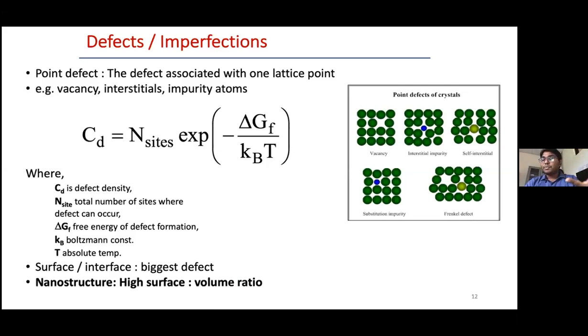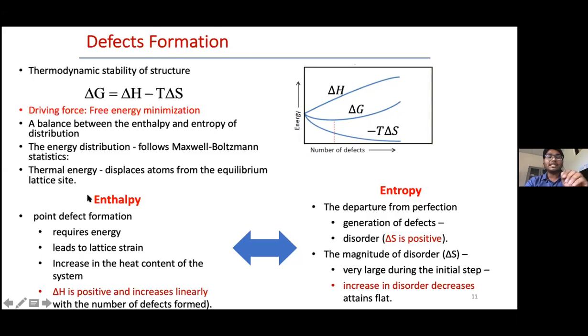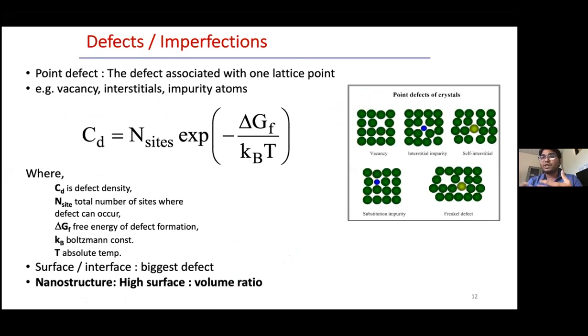And essentially the temperature of the solid, as you go on increasing the temperature, the disorder in the system will increase. You will have more defects created, because the thermal energy, as we have mentioned here, is basically one which displaces the atom from its equilibrium position. So at higher and higher temperature, more and more thermal energy is available, which is reflected in the kBT. So this equation basically sums up that if N sites is the total number of sites where the defect can occur, which is essentially the total number of sites in a lattice, then it goes exponentially with E_d by kT. So the C_d is the defect concentration for a given temperature, and so forth.